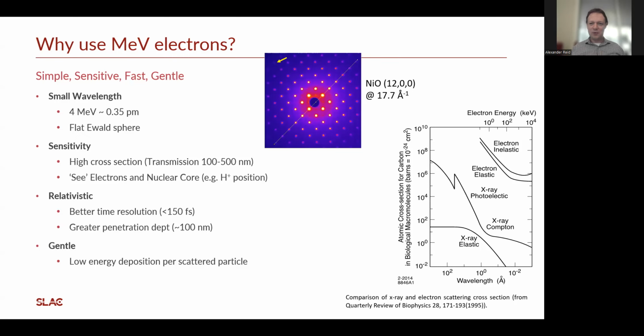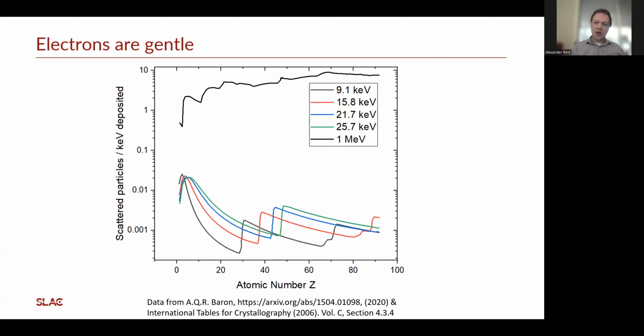Finally, I think probably one of the least appreciated things about MeV electrons is that they're a relatively gentle structural probe. There's actually not as much energy deposited per scattering event as with X-rays. And this graph illustrates this, showing as a function of atomic number for all the elements, a comparison of the number of scattered particles you can get per unit of energy deposited into the system.